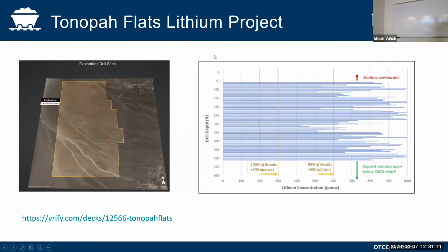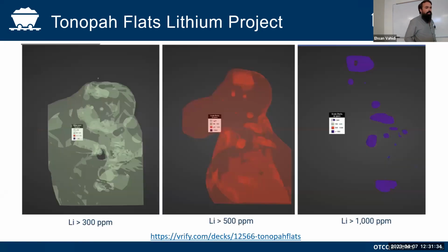This is a 3D rendering of our lithium deposit, outlining where our drill holes are. We can see that 100% of our initial drill holes have lithium in excess of 300 ppm, with almost 90% greater than 600 ppm. Looking at our deposit, almost the entire claim has lithium in excess of 300 ppm. As we move to higher and higher grades, these plots show where the optimal pits would be to start our mining process. The whole area is basically greater than 300 ppm, a good majority is greater than 500 ppm, and then we have the concentrated regions you can see on the far right figure.